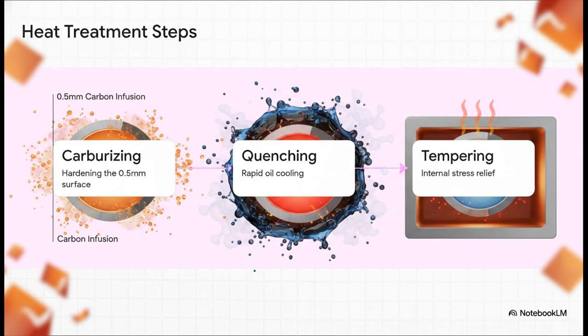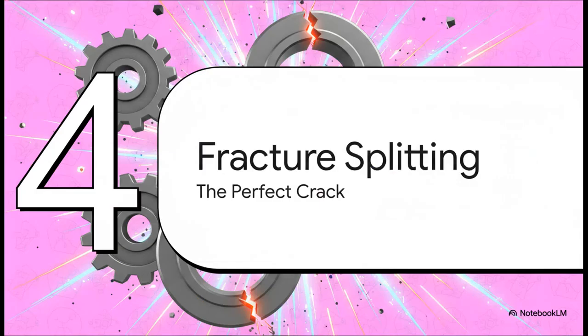This transformation happens in 3 rapid-fire sequential steps. First, carburizing infuses the outer 0.5 millimeters of the steel with carbon. Second, the glowing hot rod is violently quenched, rapidly cooled in an oil bath to instantly lock in that surface hardness. And finally, it goes through tempering, where it's gently heated in an oven to relieve all the internal stresses caused by that violent quenching. Let's move to Stage 4 and see how this builds up to my favorite part.